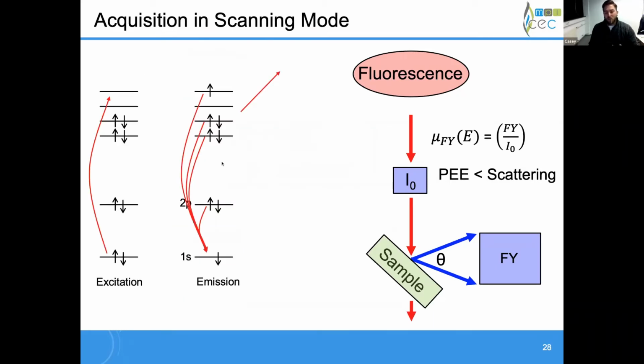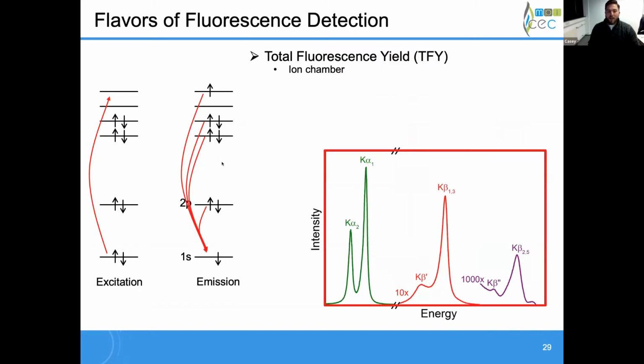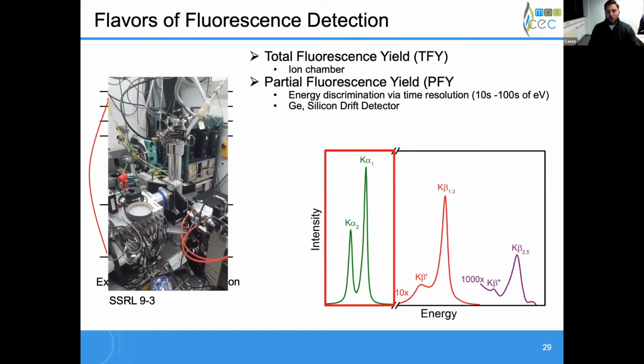Of course, because we're looking at fluorescent photons, there are a lot of different options and flavors of fluorescence spectroscopy, looking at relaxations from all these different kinds of sublevels, as well as Auger electrons. The simplest way is total fluorescence yield, where we observe all fluorescent photons; effectively we go over our entire range of emission. We could also do partial fluorescence yield, where we use solid state detectors that are capable of discriminating energy over a relatively wide gap, but it still can narrow things down to, say, the K alpha lines.